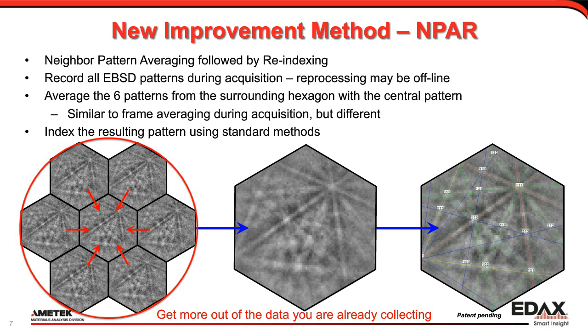You get a new diffraction pattern — illustrated in the center of the image — which is the average. Now you do your traditional indexing methods using any of the parameters you need to index it. You re-index that diffraction pattern, get new indexing, and then get new maps from that. So now what we're doing is getting higher quality data out of the diffraction patterns you've already collected.